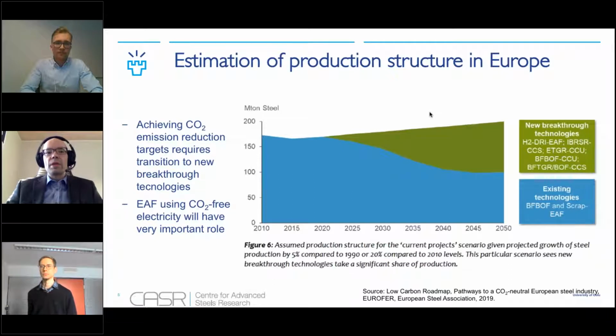And then we continue the estimation of the production structure in Europe, achieving these very challenging CO2 emission reduction targets. It requires transition to new breakthrough technologies, which can be, for example, hydrogen-based DRI used in electric arc furnace. There could be top gas recycling in the blast furnace, and then also carbon capture and storage and carbon capture and utilization. But we can see that the role of the electric arc furnace will be bigger than today, so that these estimations are based on the scenario that approximately 60% of steel production is based on the electric arc furnace process.